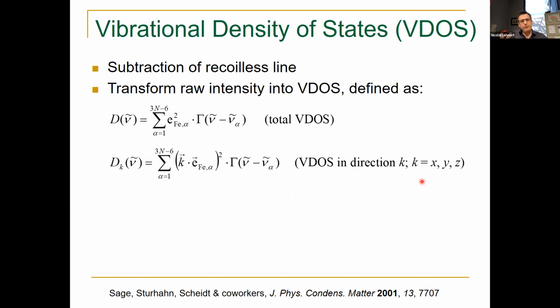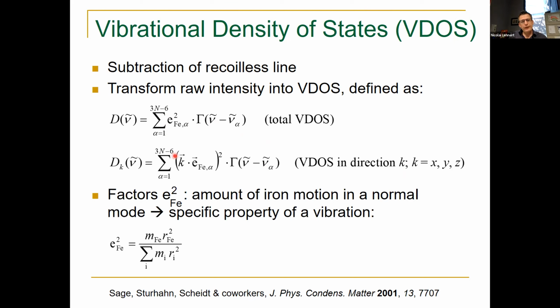So of course, what's more practical is to actually look at the data, transform it into the vibrational density of states, because in the vibrational density of states, you have this very simple relationship, right, where the intensity now of the signal in the vibrational density of states just depends on this E² factor here multiplied with some kind of band shape function. You can also look at the directionality now of the motion, so the direction in which ion is moving, and then this E² factor here, this intensity factor, can be directly related to the atomic displacement vector from normal coordinate analysis. And I'll come back to that in a little bit, but there's this very simple relationship which allows us to calculate the spectral intensities.